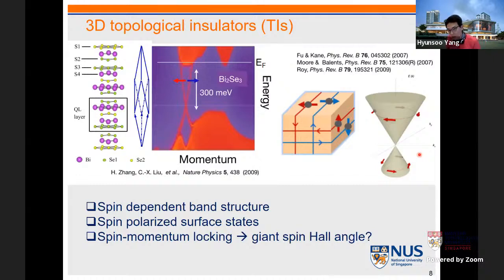So starting from the three-dimensional topological insulator, one of the typical materials is bismuth selenide. If you look at the band structure, it looks like this crossing, Dirac material. But more interestingly, if you look at the detailed spin configuration, the right branch supports this blue spin, and the left branch supports this red spin. If you look at the real-space diagram, if you apply the current along the x direction, the supported spin will be y. But once we apply current along the minus x direction, the supported spin should be minus y. So basically, you can imagine this is like a spin highway.